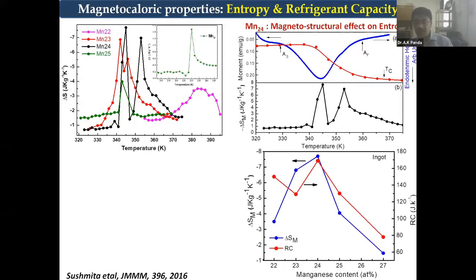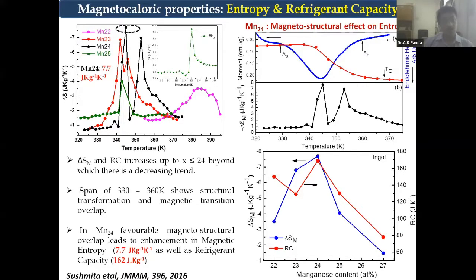So this is also a plot of entropy change with respect to the refrigerant capacity. Refrigerant capacity, as I told you, is a product of entropy and the width of the operating temperatures, that is the low temperature and the high temperature. So what do we get from here? Basically, the delta SM, the magnetic entropy, and RC, the relative refrigerant capacity, increase up to a composition of 24 to 25%, and beyond that it goes on decreasing.